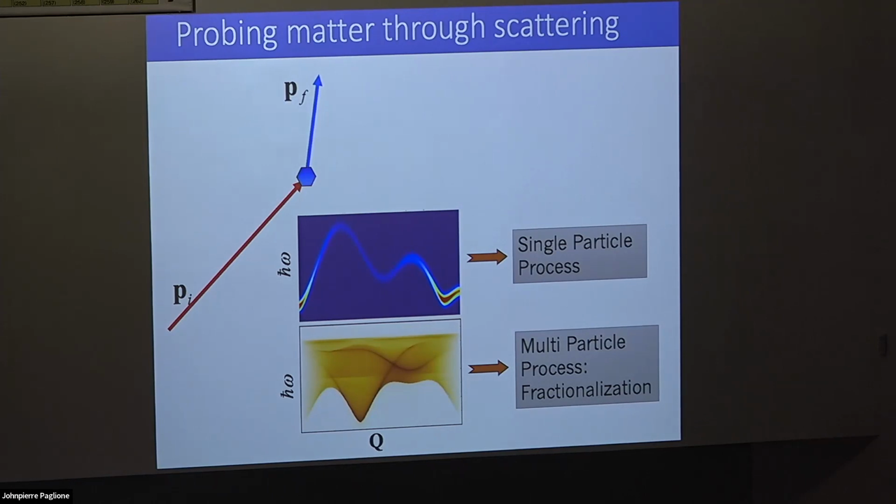and so you're really measuring some kind of a mixture of the response of the periodic system with some kind of a density of states of magnetic excitations. We can really see that experimentally as the quality degrades. Basically, all of these regions that should be empty now begin to fill up, and it's not because of damping of the modes. It's really because of loss of momentum conservation. The neutron comes in and scatters from some localized object, which is the disorder in the structure. So it's really important to advance the quality of the materials, and also to really know the quality of the materials.